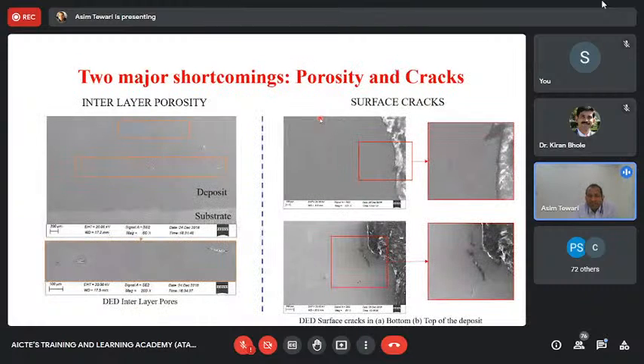Now, another very strange thing which we have seen is that there are lots of cracks. If you see this, you can see this crack coming on this. These are additively manufactured parts through directed energy deposition, Ti-6-4 and other materials, and you start having these cracks in them. Now, this is very strange. Why would a crack come? A crack means that the material broke, but it usually breaks when we put it under a tensile test. Here we have not done any of those things, so why is it breaking? That's where we realize that it is breaking because there is internal residual stress.